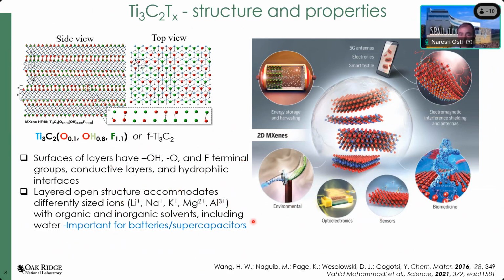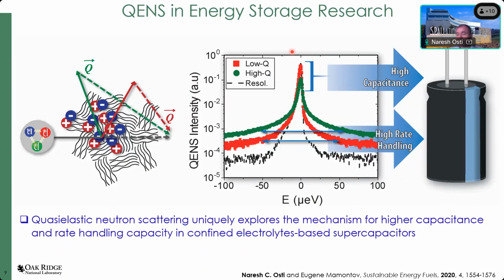The focus of this talk would be the application of the MXene for the energy storage. Now, when it comes to the energy storage, how can you relate the measurement that you do or the information that you can get from quasi-elastic neutron scattering with that of the energy storage? As I said before, the quasi-elastic neutron scattering signal, from which you can extract the width of that signal, and from the width you can get the diffusion coefficient.